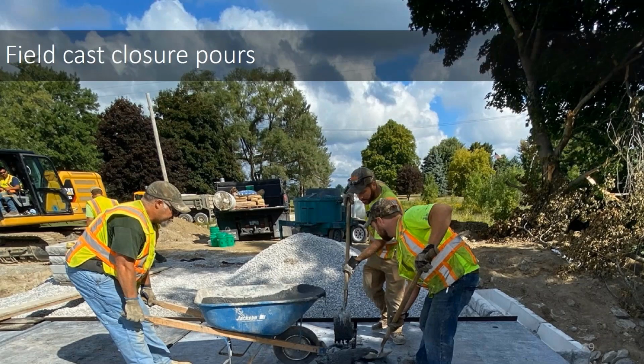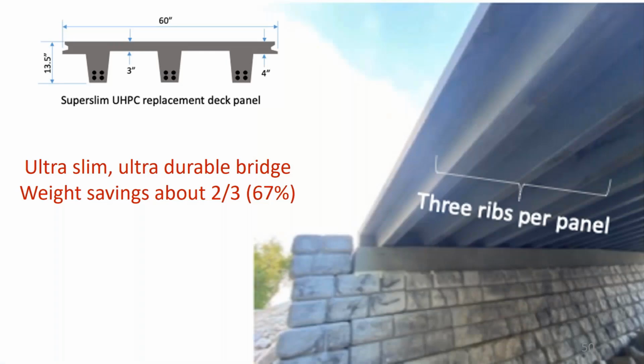On site, you can see that little turquoise mixer. That's our paddle mixer. We have mixed this plenty of times on site, so this was easy for us. The joints are super small, which we love. This stuff wants to run, and if you have large joints, just FYI, it will push through your joints and through your forms, and it'll go out where you don't want it to go. So the forming has to be watertight because it will run, and you'll have a mess on your hands. As you can see, here's the 3-stem bridge unit.